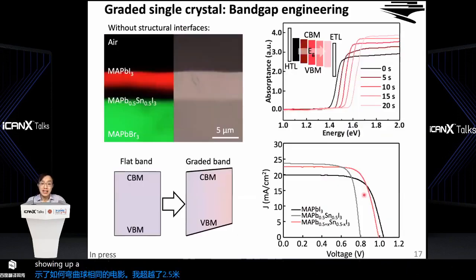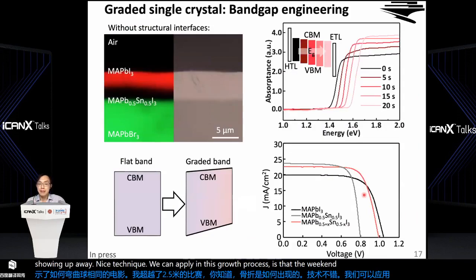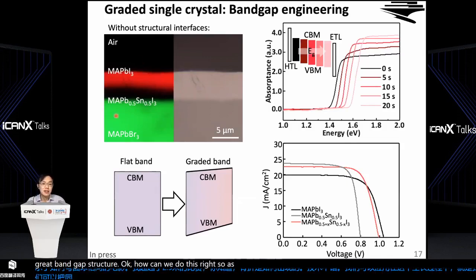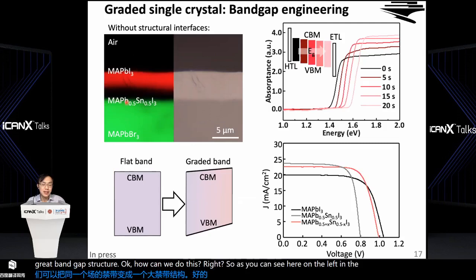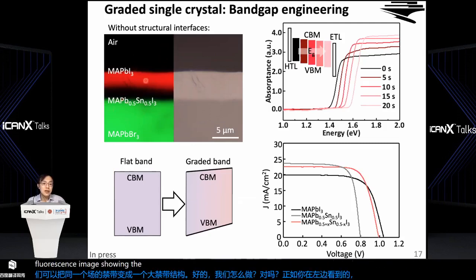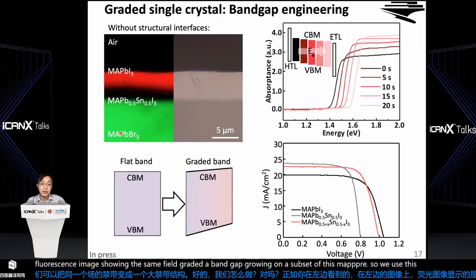A very nice technique we can apply in this growth process is that we can tune the band gap of this thin film into a graded band gap structure. Okay, how can we do this, right? As you can see here on the left-hand side, the image is the fluorescent image showing the thin film with graded band gap growing on a substrate of this MAPbBr3. So we use this material as a substrate. So this is a bulk substrate.